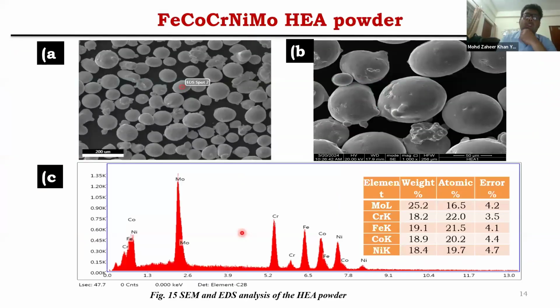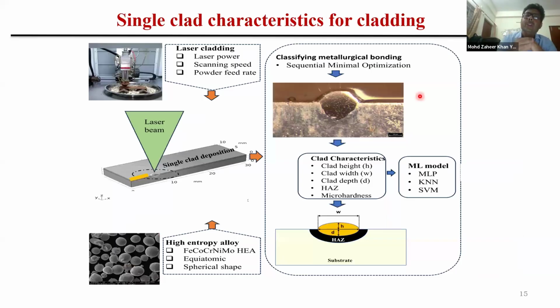So this is how the powder looks. Let us say in one of the examples, a high entropy alloy powder was used. You can see that it has equimolar content of iron, cobalt, chromium, nickel, and molybdenum. So it's a 5 system HEA powder that has been used. And with EDX, you have to always confirm. The SEM will tell you whether the morphology is round or not, because the morphology affects its melting performance.